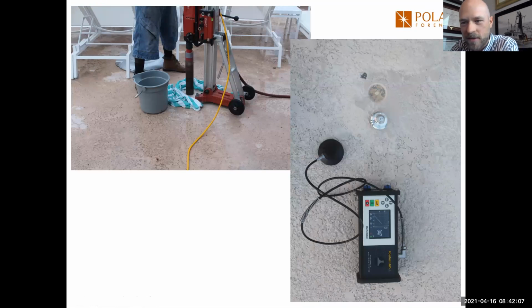So I visited the site. I did a very thorough visual evaluation. In addition to that, we also collected some concrete core samples so that we could perform petrographic examination on them. And this is now the second or third time I've mentioned petrographic examination. What that is with regards to concrete is that it involves looking at that concrete sample under high magnification.